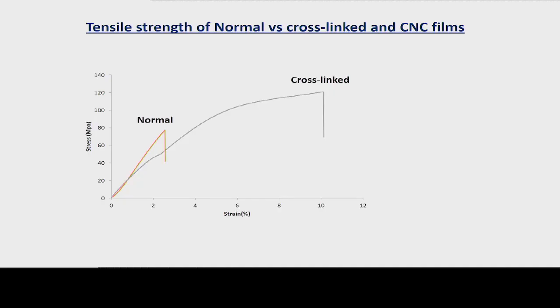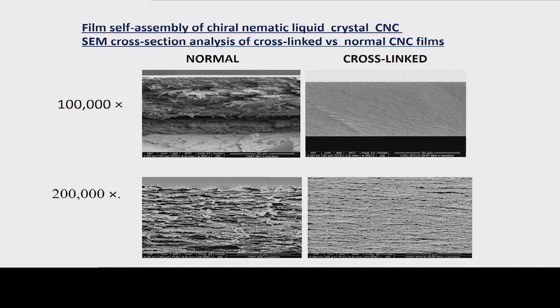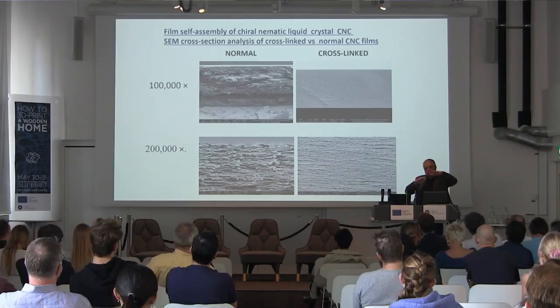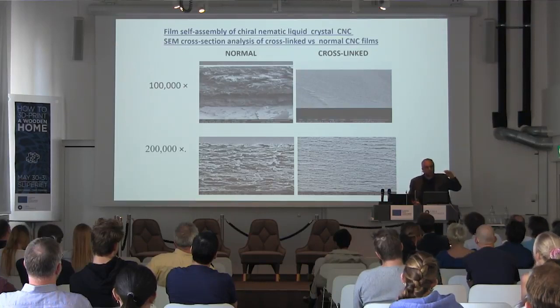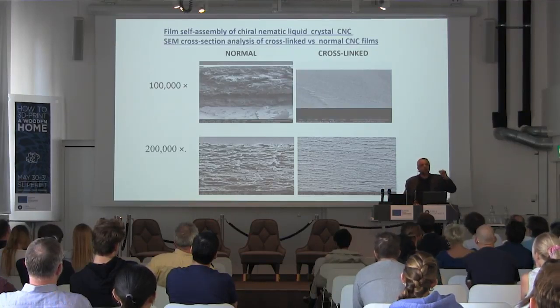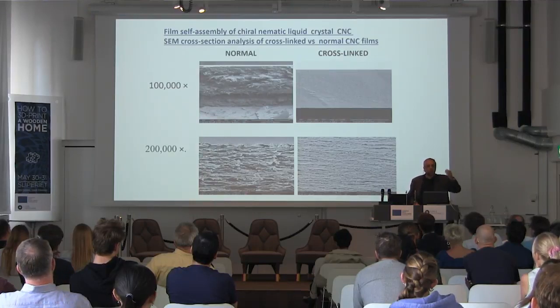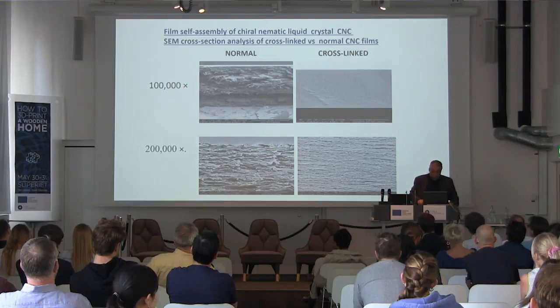And just to give you a feel how strong it is, it's about twice as strong as epoxy resin. And remember, there is absolutely no covalent bond there. It's only hydrogen bonding and van der Waals interactions. In addition, if you add certain cross-linkers that are very useful in the textile industry, you can even increase the mechanical properties. In fact, if you look at the cross-section of this material, you can see very nicely that it is actually organized in layers. And between these layers, there are some gaps that enable us to introduce some other nanoparticles to change, for example, spectral properties or other physical properties of the films.